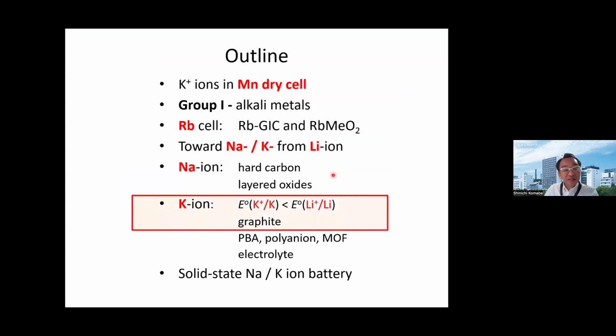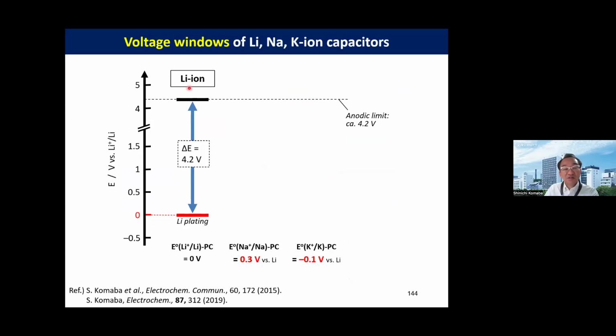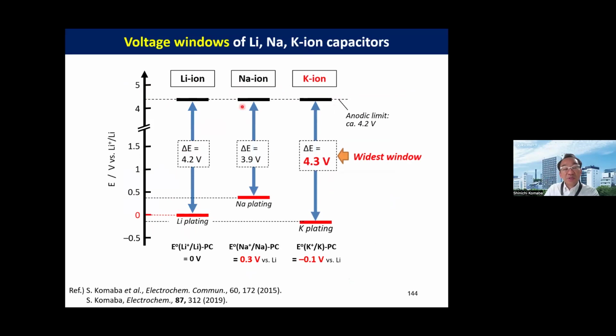So next topic is potassium ion. The standard redox potential of potassium is lower than lithium. Look at this picture. If we assume that the potential window is limited by plating and also the anodic limit, which is due to the electrochemical anodic decomposition of the organic solvent, then we can assume that sodium and potassium have the same anodic limit.